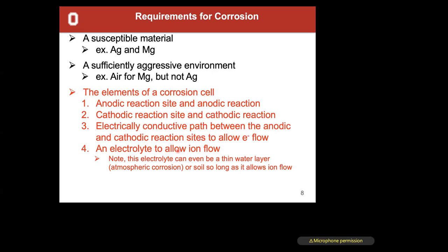So typically when we think about inhibiting corrosion, we're actually accessing these elements right here. We're either covering the surface with a paint or something, so the electrolyte can't touch it. We might also be killing the conductive pathway. When you have 2 materials that are touching each other, you can kill a conductive pathway and stop corrosion from happening.